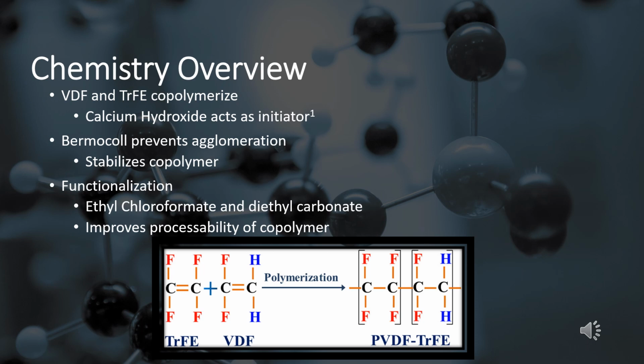Our calcium hydroxide will not be a typical initiator in the sense that it will not form any free radicals or any other reactive species that initiate the reaction. However, what calcium hydroxide will do is it will initiate the copolymerization reaction between both VDF and TrFE by deprotonating the acidic hydrogen atoms on the carbon atoms of VDF and TrFE monomers. This reaction will generate carbanions, which are highly unstable, and they will attack the electrophilic double bond of the neighboring monomer, leading to chain growth and propagation. The use of calcium hydroxide as a base initiator is a common method for initiating polymerization for reactions that usually involve monomers with acidic hydrogen atoms, such as in our case VDF and TrFE.